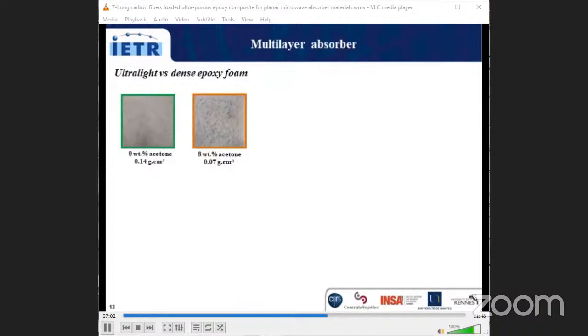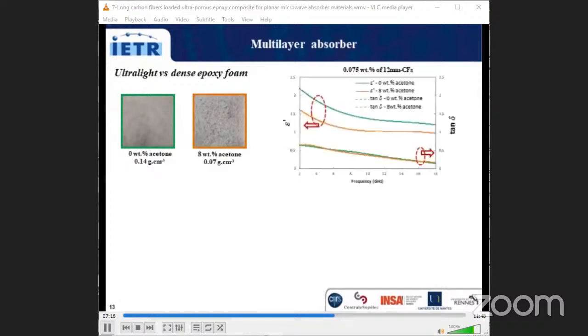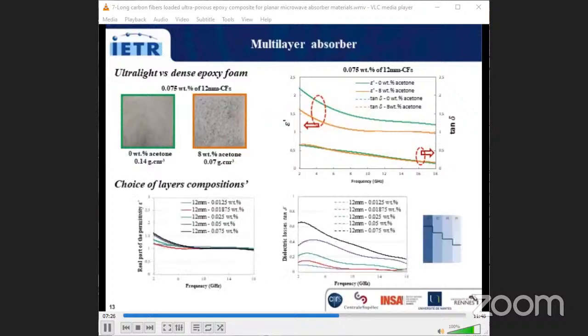In this part, I present the ultralight foam with 8% of acetone loaded with 0.075% of carbon fiber, compared to the standard foam without acetone. Here are the photos and the dielectric properties of these two samples in the frequency band between 2 and 18 gigahertz. Results show that the real permittivity of the sample with 8% of acetone decreases when the acetone is used.